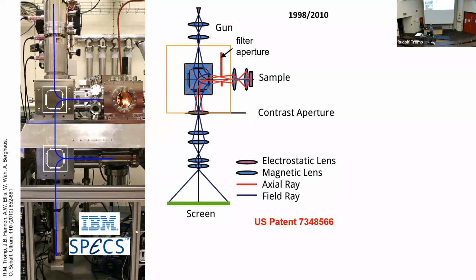But so this was the first microscope that we built, an electron gun. We go through a 90-degree beam deflector. Marian Mankos, the student that I just showed on the slide with John Cowley, he helped me design this centerpiece here. The beam goes to a sample, and the sample sits at a potential which is almost equal to the gun potential. So if you extract 15 kilovolt electrons from the gun, then the sample sits at 15 kilovolts plus or minus a few eV, depending on exactly what experiment we do.